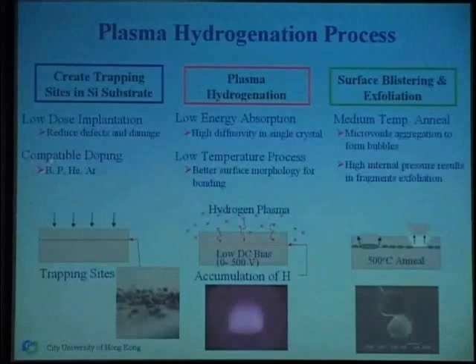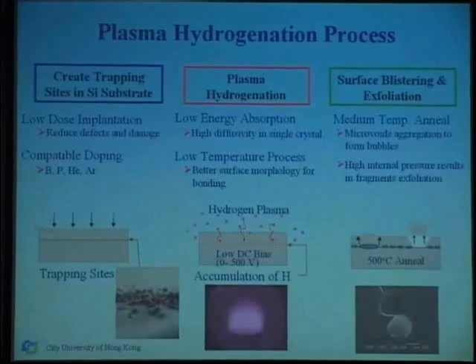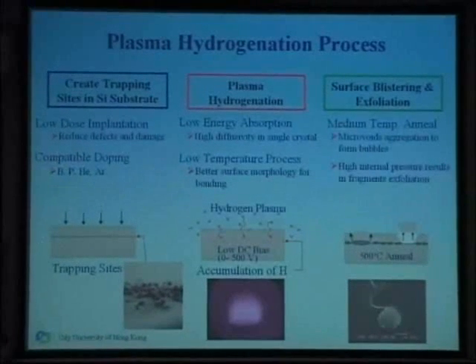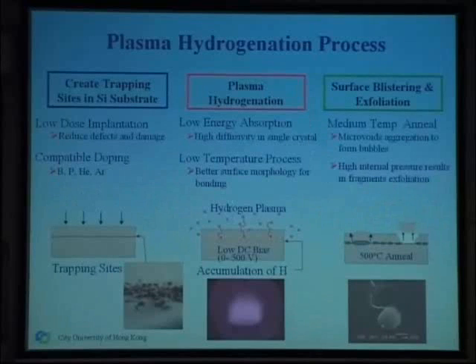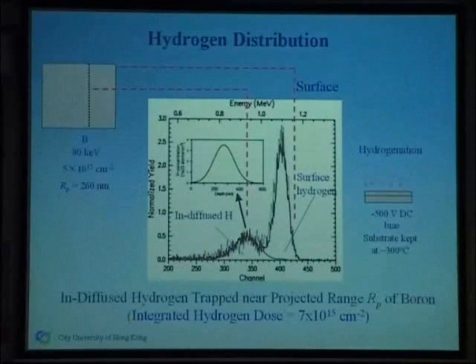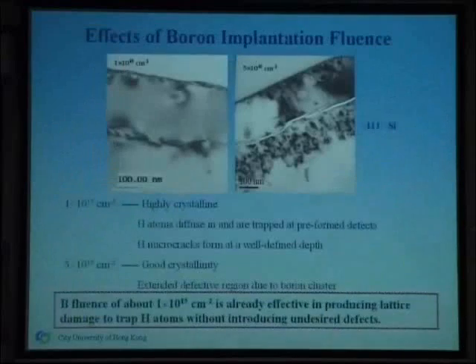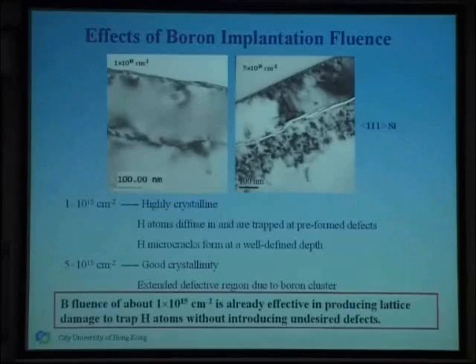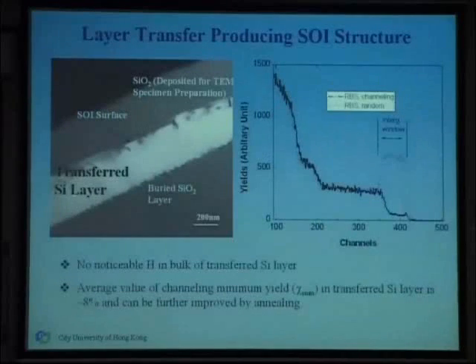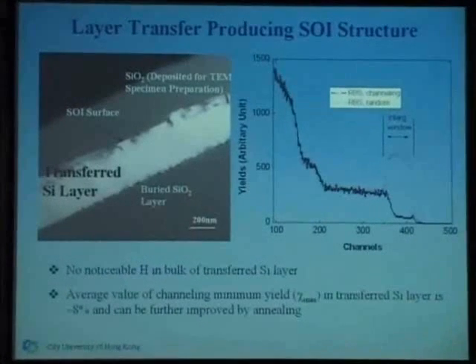And the way it's done is we first form some defects. This is the SEM. Form some defects at this site by implantation. And then we draw the hydrogen ions in from the plasma, actually atoms, right here. Low energy, so a very cheap process. And then with the bubbles formation, we can do the cleavage. The obvious data shows that it's useful. Now we have hydrogen actually at the interface right here. We can detect hydrogen, so it's successful. And you can see the defects here. Very, very linear, so you can have a very sharp breakage at this point. And with that, we're able to transfer the layer from the top to the bottom. So this is very nice. So this is basically one step at a time.